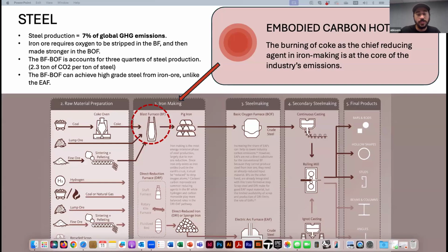And so moving on to steel, it accounts for about 7% of global greenhouse gas emissions. And at the core of the industry's emissions is the use of coke in iron making within the blast furnace. For context, most surface level iron exists as iron oxides, which is essentially rust. Iron ore needs to be stripped of oxygen in the blast furnace, which produces a molten pig iron. This pig iron, however, is unusable because it's still highly dissolved with carbon, and structural steel needs a metallic iron that's stronger and more ductile.